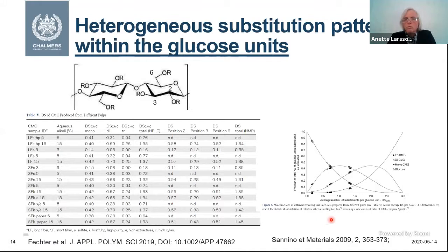That is, of course, very important information, and that will give effects on the properties of the polymers. Here's also an example where, if you take 1.3 total degree of substitution, as we have here, they show that there is a combination. This line here corresponds to when you have no substituents, so about 25% or something like that is unsubstituted. At the same time, the majority has 1 substituent, but there are also some that have 2 substituents and some that even have 3 substituents on the glucose units. So this shows that the substitution pattern within a glucose unit is very critical.